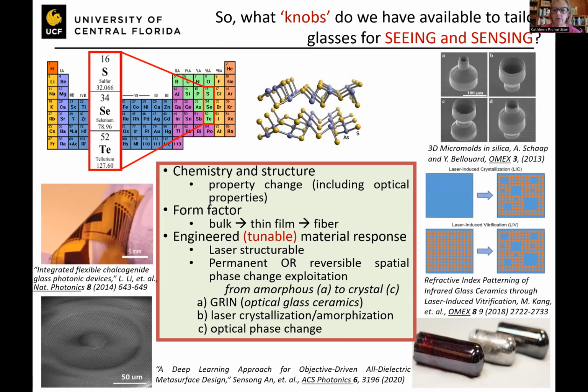Or it can make them laser structurable, whereby the laser that interacts with the structure of the glass can change its extent of polymerization and therefore make it somewhat soluble or very soluble to being etched. So here are some examples of some 3D laser written micromolds in silica made by one of our colleagues at EPFL in Switzerland, which shows that using lasers, we can either chemically or physically remove or ablate material. In our application, we showed that by taking a glass, converting it to a glass ceramic, and then using a laser, we could either reamorphize spatial regions or turn it back to glass, or start with a glass and then locally, using direct laser write, locally crystallize it. Suffice to say that some compositions do better than others. And if you understand this interrelationship, you can tune the material to have the properties you want for your applications.